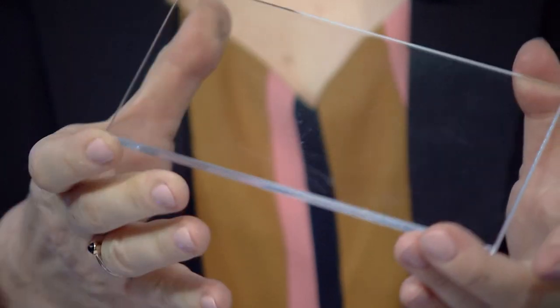How strong are polymers? People's perception is that they're not as strong as metal and glass. Polymers can be very strong thanks to properties which can be tailor-made. For example, this is polycarbonate in pure form — crystal clear, very robust. You can have it in any colour, any shape, and it's virtually unbreakable. This is used for lights already? Yes, all the headlights around the world are made of polycarbonate; it's industry standard, unbreakable, very safe. Another example: if you replace all the windows in cars with polycarbonate, your weight will go down 30 to 50 percent, and try to break into that car — you will not manage that; it's virtually unbreakable.